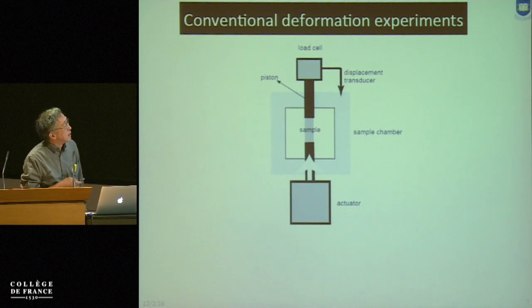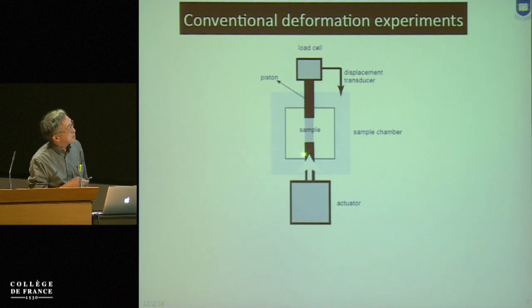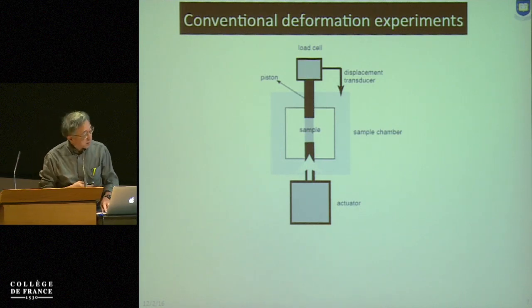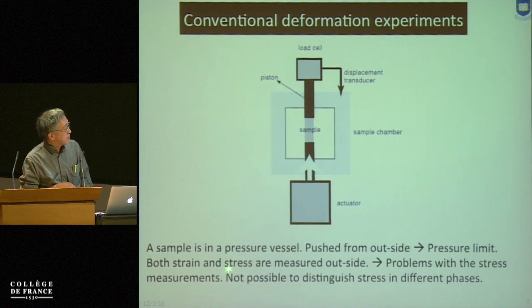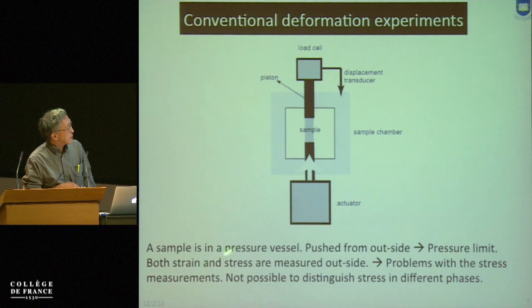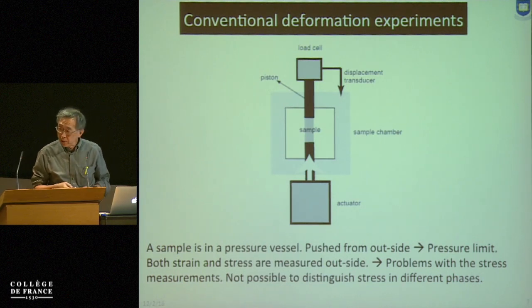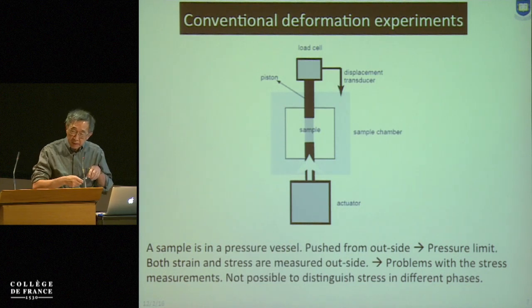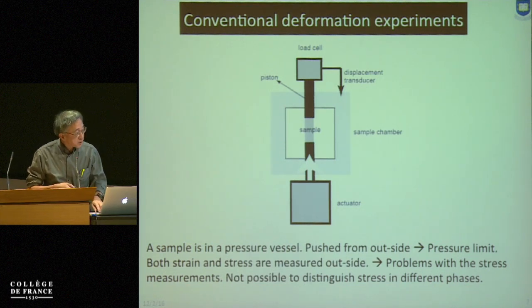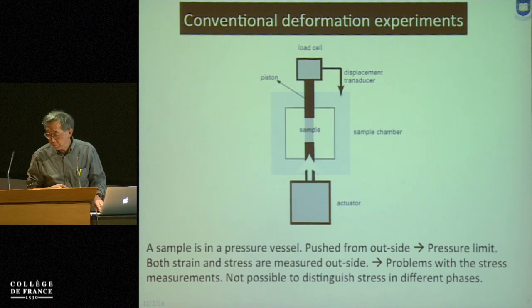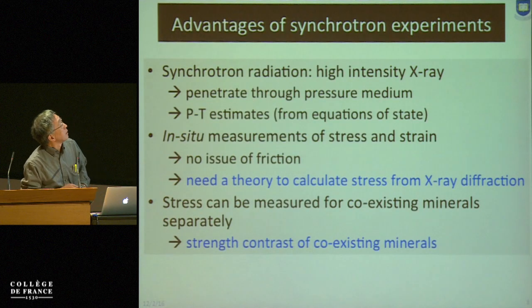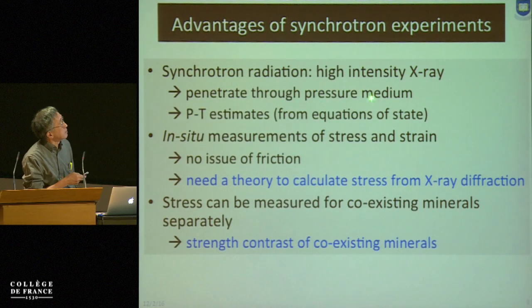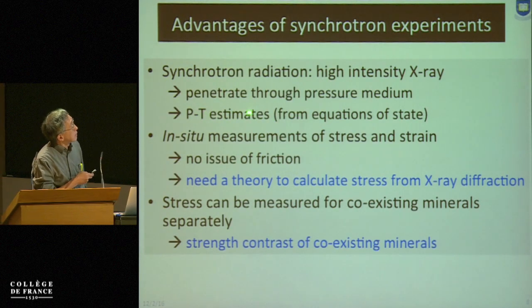So the concept of a classic deformation apparatus is that the sample is located in a sample chamber, and an actuator applies the load to deform your sample, and you measure the load with a load cell on the outside. If you go to really high pressure environments, you cannot put any load cell inside the sample chamber. So the measurement of stress and strain must be done by a completely different technique. With a synchrotron facility and high intensity X-rays, you can go to really high pressure and temperature and monitor what's going on in your sample.